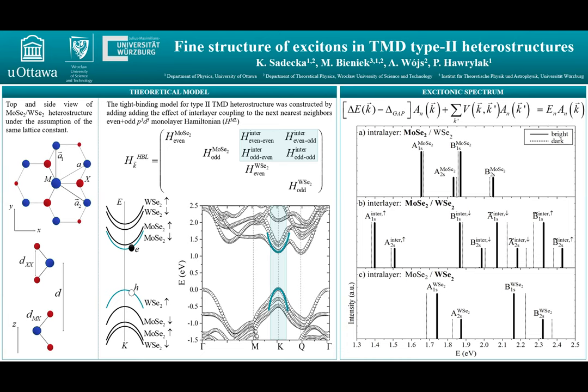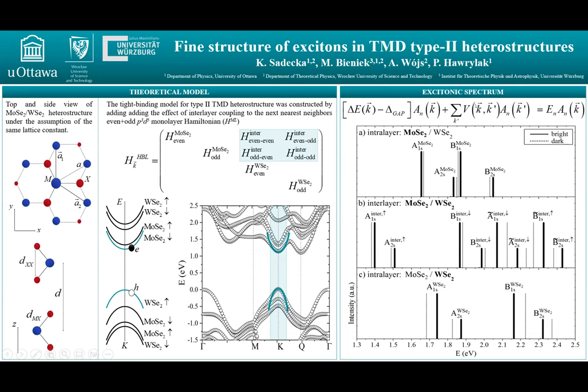Finally, we accurately solve the Bethe-Salpeter equation and determine the excitonic spectrum, as you can see on the last plot, considering both intra and interlayer excitons, and we use simplified Rytova-Keldysh additional local screening theory here. This will all allow us to finally study the effect of Moiré potential and compare it to a fully tight binding approach to excitons in twisted Moiré heterostructures.